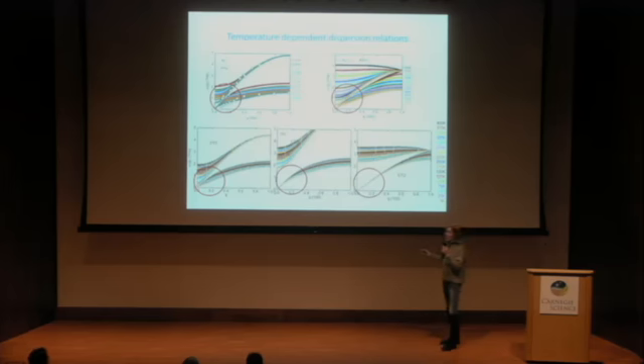So if you look at the elastic constants of these systems, you can immediately draw conclusions about the elastic constants because this must be a very hard compound, very stiff. And this has been also seen experimentally because below the structural phase transition, you should see the domain formation, and these are not easily movable, so they're very hard. And here you have the same behavior. Again, there's almost no interaction, the system is very hard, whereas these two others show different behavior.